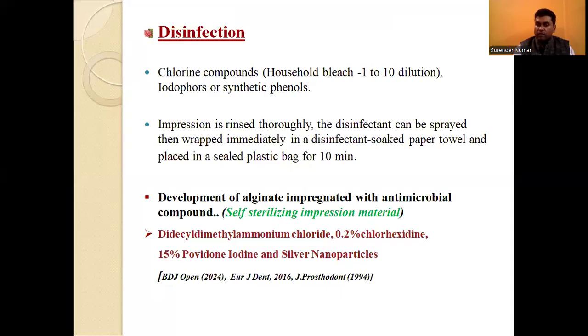Development of alginate impregnated with antimicrobial compounds, also known as self-sterilizing impression materials. That means we are adding certain compounds in the alginate which will give them antimicrobial action, like 0.2% chlorhexidine. We can add didecyl methyl ammonium chloride, 15% povidone iodine, and silver nanoparticles.